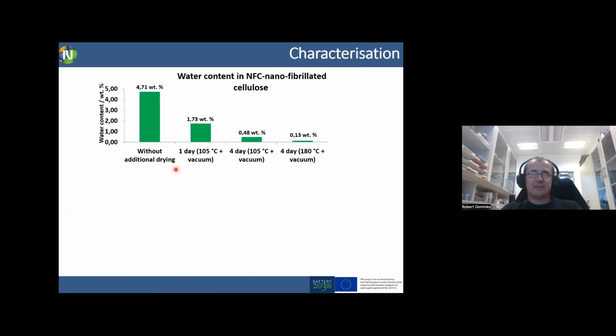The first concern was, how about water, the content of water inside the cellulose? We know that cellulose is hydrophilic and it attracts a lot of water. Without any additional drying, even a dry mass of cellulose still contains around 5–8% of water inside. But with careful drying, you can really decrease this quantity.